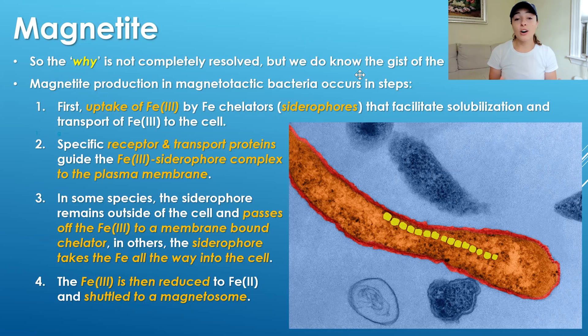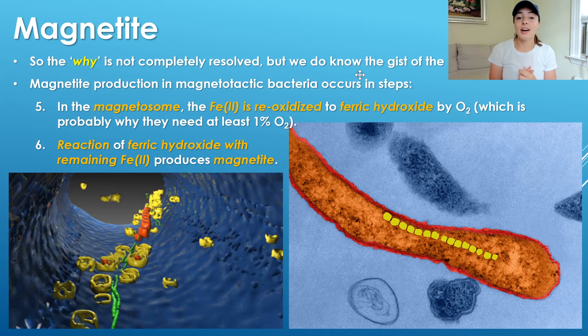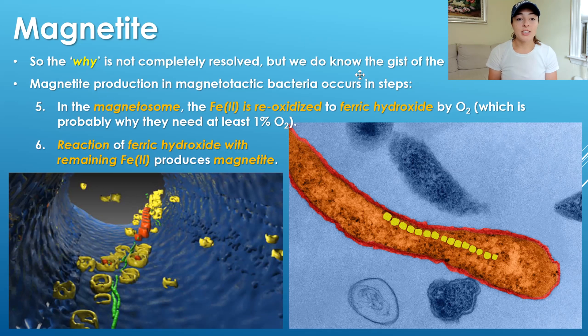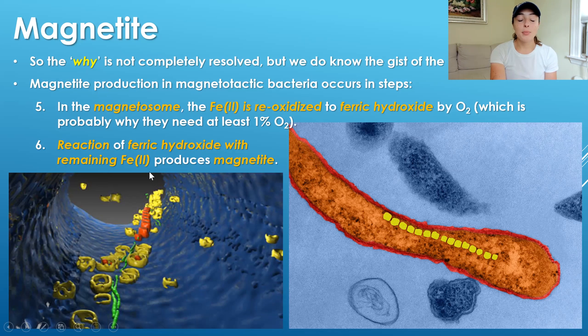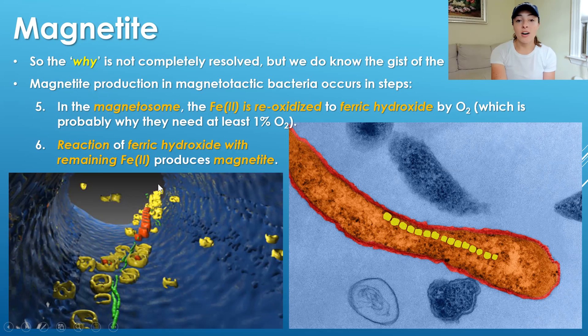Regardless, once the iron is in the cell, iron 3 is reduced to iron 2 (ferrous iron) and shuttled to the magnetosome. In the magnetosome, iron 2 is reoxidized to ferric hydroxide by oxygen — which is probably why they need at least 1% oxygen to synthesize magnetite. Then the reaction between ferric hydroxide and the remaining iron 2, or the continued stream of incoming iron 2, produces the magnetite. We can see an animation of this: the inner part of a magnetotactic bacterium, with the magnetosomes hosting magnetite formation, and then the magnetite forming chains that align along geomagnetic field lines.